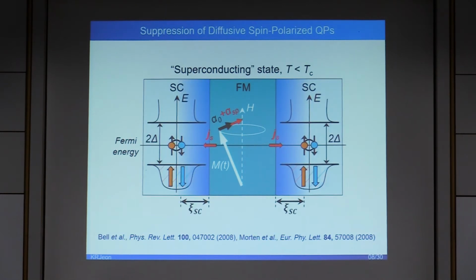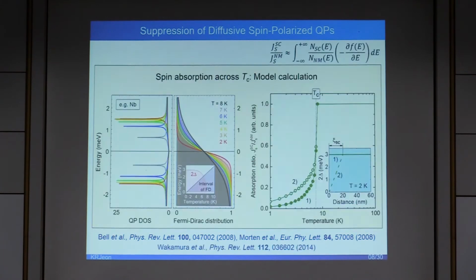which describes how quickly the magnetization precession relaxes. On the other hand, in the superconducting state below the Tc, when the superconducting energy gap opens, spin angular momentum of magnetization in the ferromagnet can mostly transfer to the singlet superconductor through quasiparticle excitation. With decreasing temperature, the superconducting gap and the energy of available quasiparticle states increase, and thus the transport of dynamically driven spin polarized quasiparticles becomes inefficient. This gives rise to the suppressed spin sink of the superconductor and thereby the reduced Gilbert damping of the ferromagnet as compared to the normal state, as reported previously.